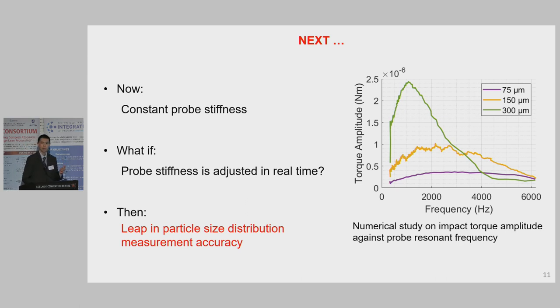This probe, with different stiffness, is sensitive to different size distributions. At the moment, the stiffness is constant, so it has limited further improvement of measurement accuracy. What if the probe stiffness can be adjusted in real time? In this case, we will be able to see a giant leap in measurement accuracy improvement.